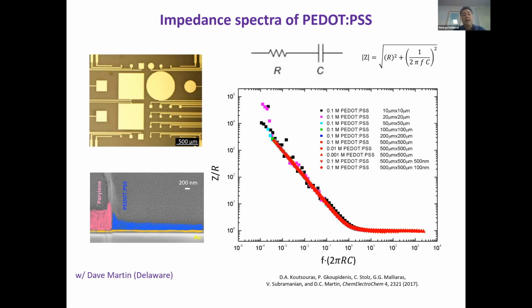This is impedance spectroscopy that we've done together with Dave Martin when he was on sabbatical with us. I'm sure you know Dave, he's been one of the pillars of this community. We made electrodes with different shapes, different sizes, coated with PEDOT films of different thickness, and used PEDOT:PSS that was deposited either electrochemically or by spin coating. This was very laborious, very painstaking work. For every electrode that we made, we cross-sectioned it using FIB, focused ion beam, and we very carefully accounted for edge effects, making sure that we know the exact volume of the film and that the films look to be of very high quality. So literally hundreds of impedance spectra, hundreds of cross-sections.